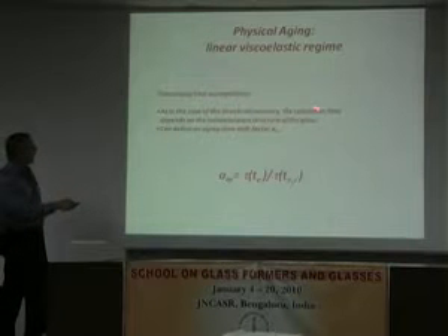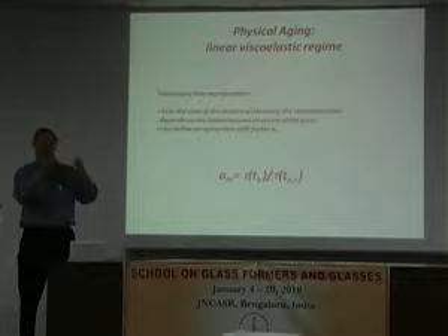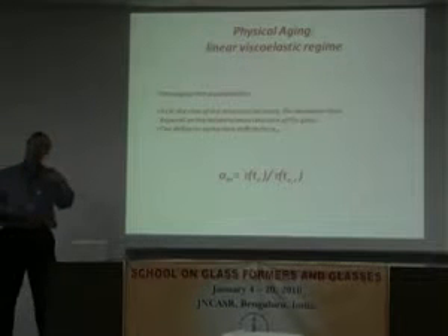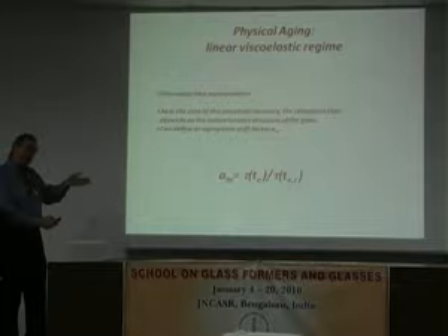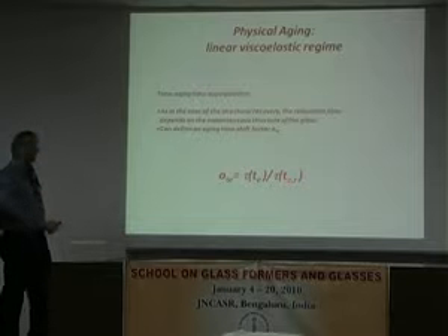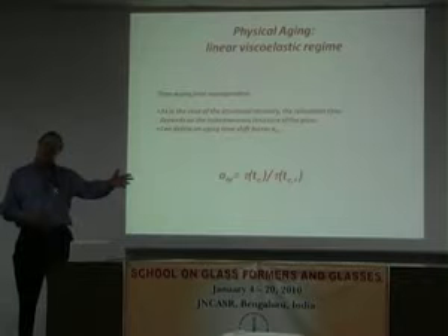Okay, so as we talk about aging time superposition, as in the case of structural recovery, the assumption is that the relaxation time depends on the instantaneous structure of the glass. Otherwise, you don't make that aging time superposition caveat. But remember, there's a measure of the structure of the glass, and it could be enthalpy, it could be volume, or if you could be more complete, maybe including some internal ordering parameter. In my case, I'm going to usually use the surrogate of volume, because that's what we measure. And then we can define this aging time shift factor, as I did graphically. The aging time shift factor is just the tau at some aging time divided by the tau at some reference aging time. You either take it as your first test or your last test. It doesn't really make any difference. It just shifts the curves, right?